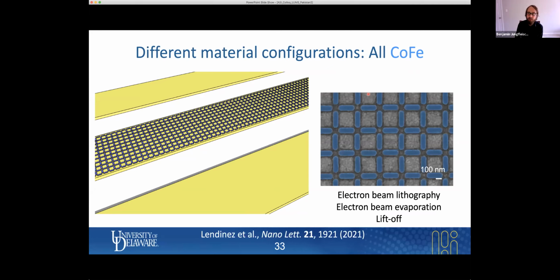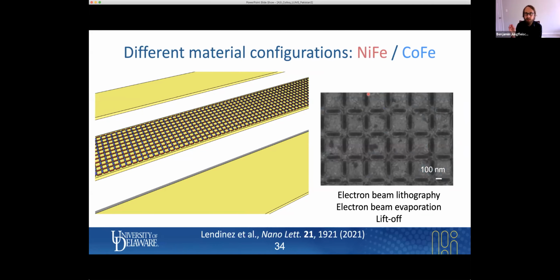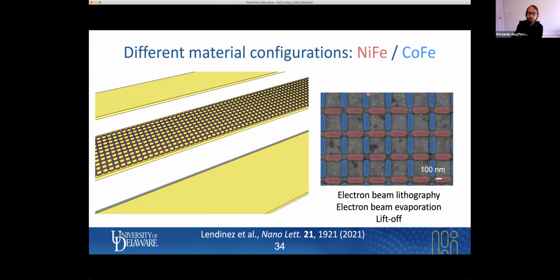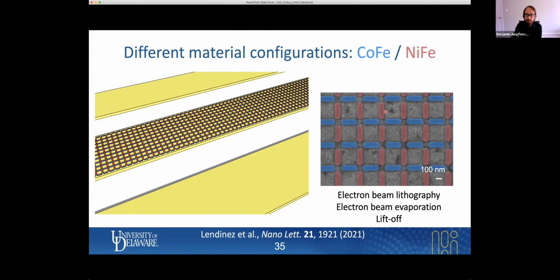And then we defined bicomponent arrays, here with nickel iron on the horizontal elements and cobalt iron on the vertical elements, and the complementary lattice with cobalt iron on the horizontal elements and nickel iron in the vertical elements. And again, I'm doing this just because of the relationship of the RF drive, so the Ørsted field, and the direction of the elements. And you can see from these SEM images that we got a really nice alignment of these elements. So this is a two-step electron beam lithography work.